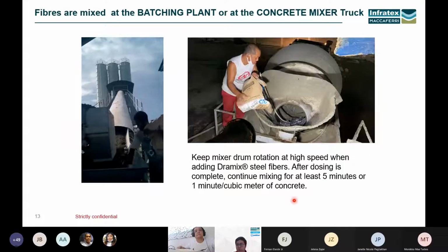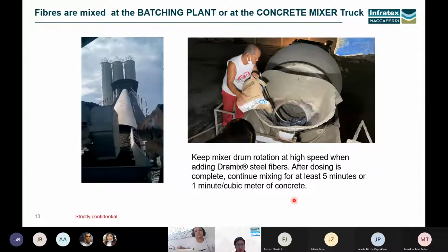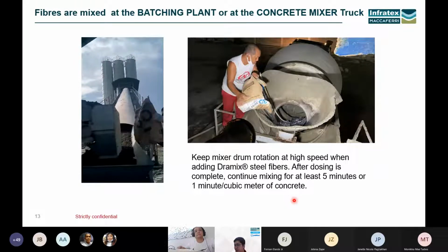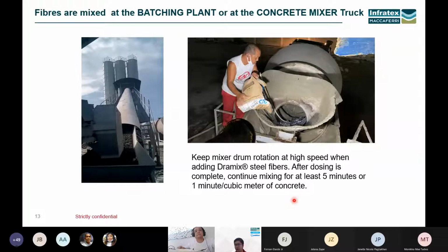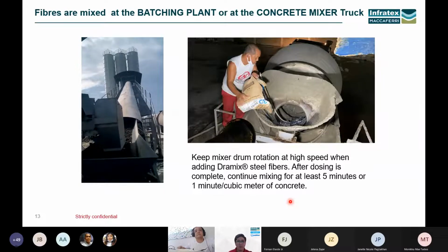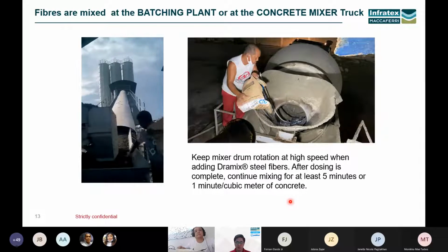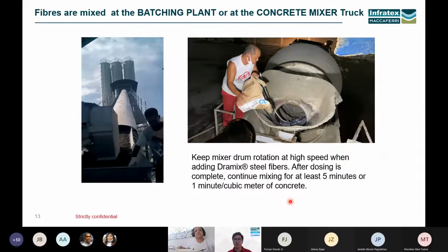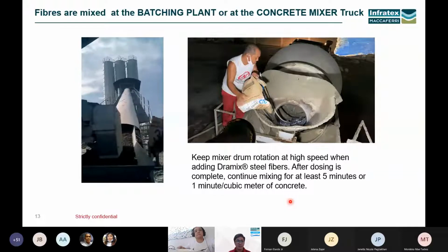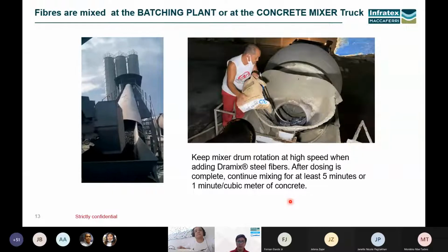The next step would be the dosing of steel fibers, either at the batching plant or concrete mixer at site. Still, we recommend to do that at the batching plant through the conveyor and central mixer because it will allow us to dose and achieve the uniform distribution of steel fiber a lot faster.